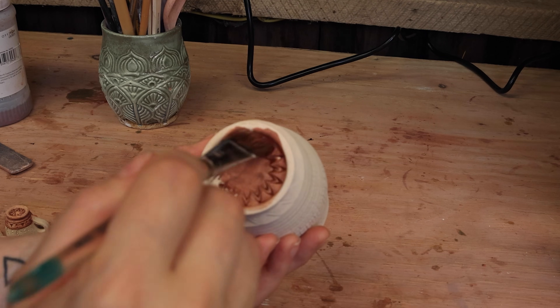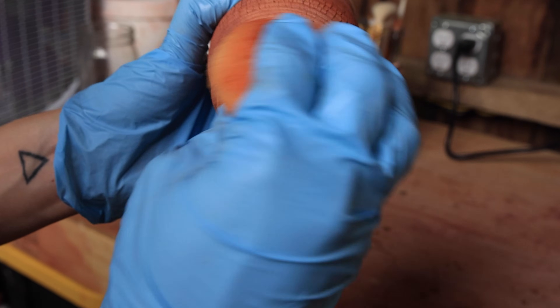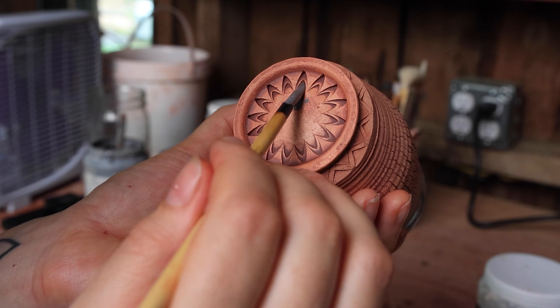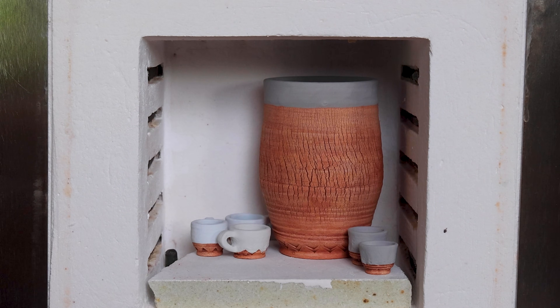I'm interested to see how iron oxide works when it's fired at a fast rate. Once I have all my iron oxide applied, I go ahead and glaze everything. I'm using pre-made glazes for this, and I chose glazes that I thought would be able to withstand a rapid firing and didn't need a slow firing, because this kiln heats up really fast. The kiln has fired — it fired to cone six, and I held it for 10 minutes. I'm amazed it only took a little bit more than an hour to reach temperature; my other kiln takes at least 12 hours. I'm going to open it and see the results — I'm very excited.